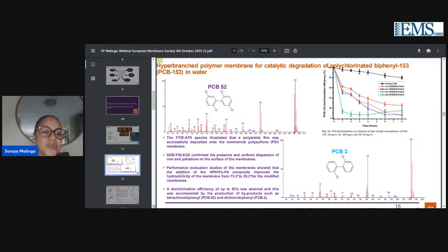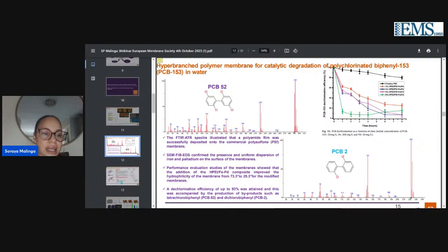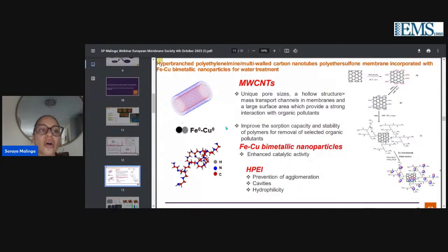So we were successful in the dechlorination of this targeted compound. We then also further used the hyperbranched in first preparing another bimetallic system, iron and copper, in a multi-walled carbon nanotube. So what we first did was functionalize the multi-walled carbon nanotube with carboxylic acid so that we could link it with the NH2 groups of the hyperbranched polymer.